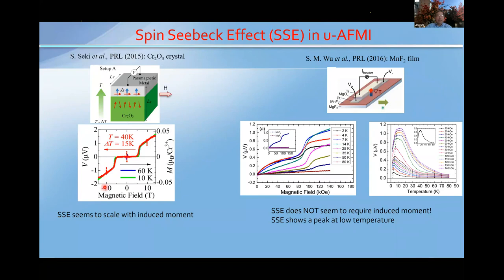Let me briefly summarize the result on the left, by Seki et al. They found that the spin Seebeck voltage is essentially zero until the easy axis field reaches the critical value, which is the spin flop transition. Then they overlaid the spin Seebeck voltage with the magnetic moment measured in SQUID, I think, and these two curves are essentially on top of each other. That indicates the spin Seebeck voltage, a measure of the pure spin current generated by heat, is driven by or related to the induced moment.